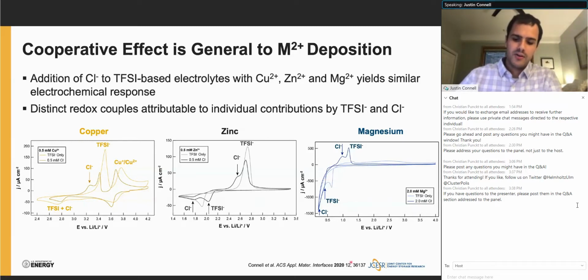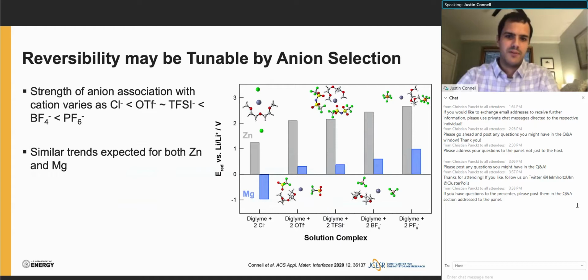No, we'd also like to know, I made the point at the beginning of my talk, can we mimic what chloride is doing? Does this effect extend to other anions? And so to understand what trends we might expect, we turn again to DFT, and we see that as we start to play around with anions of differing association strengths, we do see a consistent trend of a shift in the redox potentials. We move from more strongly associating anions like chloride to very weakly associating anions like PF6. And we expect very similar trends for both zinc and magnesium.